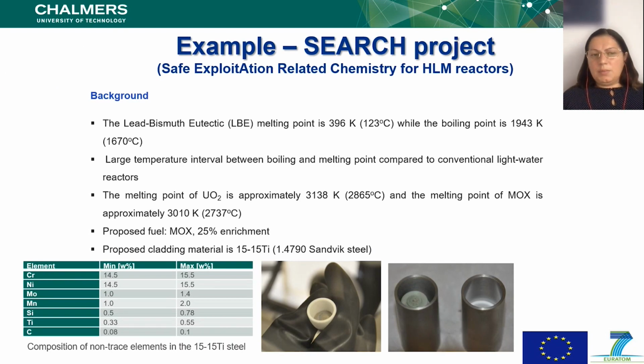And some examples of what do we look at? Well, we can look at the lead bismuth, which has a eutectic point of 123 degrees, and it's quite good because the boiling point is very high. That means that you have a very good coolant for the reactor. And then you have the possibility to have different types of fuel which can be used there. And then we looked at the interactions between the fuel, the coolant, and the cladding. And the proposed material is the one I told you before, the 15-15Ti, so it's not a zircaloy anymore in this case. Next, please.